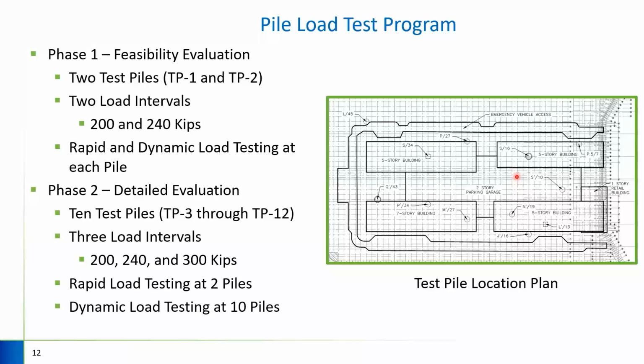We went into the detailed evaluation. And the purpose of the detailed evaluation was to do more of a parametric study across the entire pier footprint instead of 2 individual locations, to make sure that the pile capacities were acceptable, not only in the areas where we had the deepest embedment into the glacial till and weathered bedrock layers, but also shorter embedments in those layers, shorter piles versus longer piles, and things of that nature. And so for this particular portion of this, we ended up doing 3 loading intervals: 200, which was the base load that we had discussed before, the 240, which resulted in some cost efficiencies, and then ultimately the 300 kips, which was the maximum load that the structural engineer permitted per their design.